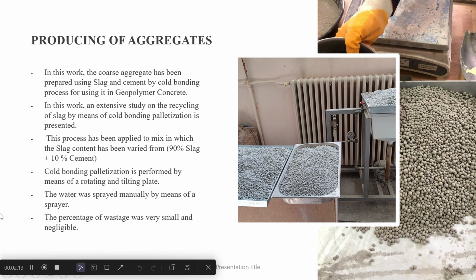As you can see in this slide, how to produce the aggregates. In our work, the coarse aggregate has been prepared using slag and cement by cold bonding process for using it in geopolymer concrete. In this work, also an extensive study on the recycling of slag by means of cold bonding pelletization is presented.